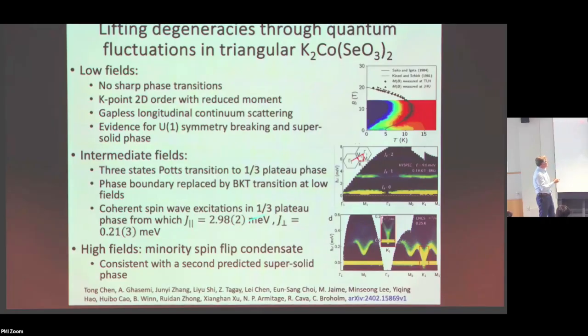At intermediate fields, we have this one-third magnetization plateau from which we get the Hamiltonian, and we can see that it is really a three-state Potts model. And then at really high fields, we have this additional little sliver of a phase that maybe is a second supersolid. That one is difficult to look at experimentally. 20 Tesla is quite hard, but we have plans to take a look for that as well.